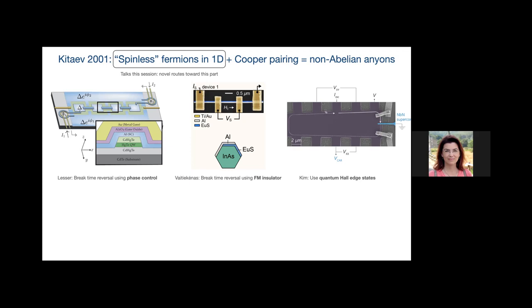I wanted to add something related also to the previous question. So you were asking if you need to close the gap in the superconductor, and the answer is clearly no. You want to be able then to proximitize the wire. So basically, this is what I showed in my talk. In the wire, you need the superconducting correlations, and you need the magnetic correlations, and you can get them through two ways. One is directly in the region where the europium is, you get there some magnetic correlations, but then you can have the extra ones that come from the superconductor, because there is also this proximity effect between the europium and the aluminum. And this extra indirect magnetization helps to get the topological phase better, to get higher topological minigaps and so on.